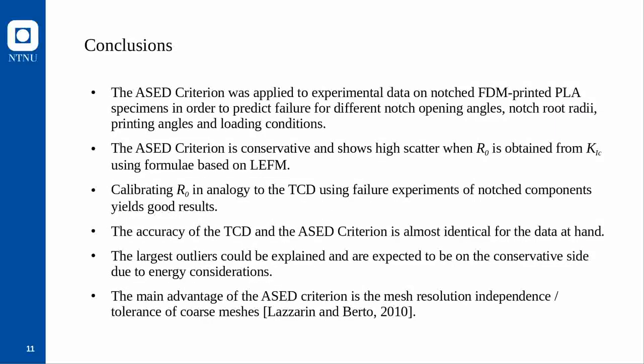To wrap up: we applied the ASED criterion to experimental data from Ahmed and Susmel (2018) on notched FDM printed PLA specimens, predicting failure across different notch opening angles, notch root radii, printing angles, and loading conditions. The ASED criterion is conservative with very high scatter when R0 is obtained from fracture toughness via linear elastic fracture mechanics formulas. However, when calibrating R0 in analogy to the TCD using experimental data, the ASED criterion yields equally good results, with accuracy almost identical to that of the TCD.